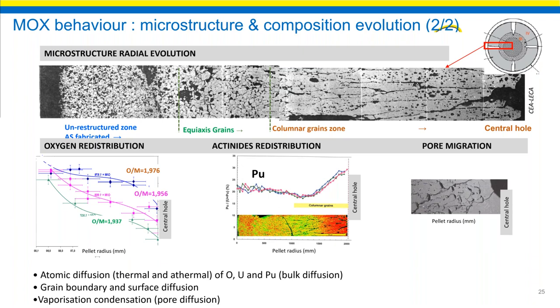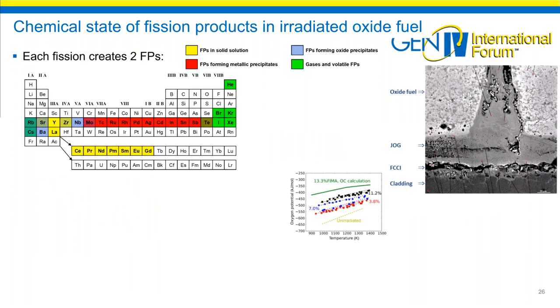Here we have the example of an initial stoichiometry of 1.97 at the end of fabrication. Close to the central hole, you can get 1.93 or 1.94, which is very low. We will see the effect. When burn-up is increasing, fission is oxidizing and thus contributes to the increase of the O over M. At a medium burn-up, the stoichiometry is close to 2.0 everywhere in the pellet. So next slide, please. Now we will speak about the fission products.